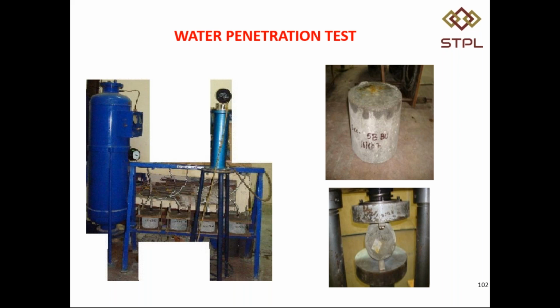Normally, these values are limited by the project specifications. Some specifications say it shall not be more than 10 mm. Some specifications say it shall not be more than 15 mm. MORTH specifies the water penetration value shall be limited to 25 mm. So we can measure only by splitting the cylinder.